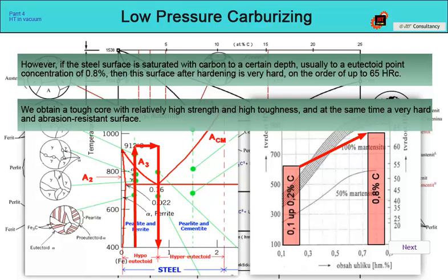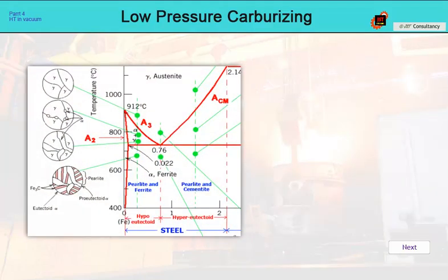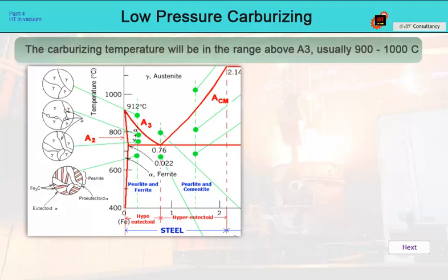Thus, we get a tough core with relatively high strength and high toughness, and at the same time a very hard and abrasion-resistant surface. The principle is therefore the same as in conventional carburizing, only the process of obtaining carbon takes place under reduced pressure. To ensure the carburizing process, the parts must be heated to the austenitizing temperature, and a carbon source is needed. Since case-hardening steel has a very low content of this element, the carburizing temperature, according to the iron-iron carbide diagram, will be high, above the A3 temperature, usually between 900 and 1000 degrees Celsius.